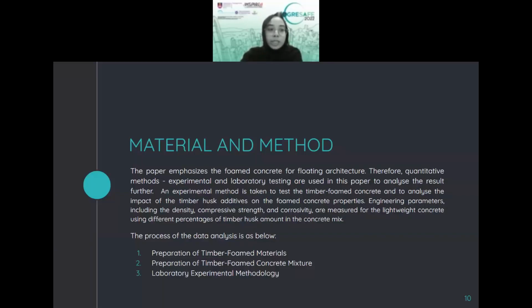And coming towards the material and methodology. In this paper, I use a quantitative method where experimental and laboratory testing are used to analyze the result further. So the experimental method is taken to test the timber foam concrete and to analyze the impact of the timber husk additive on the foam concrete properties itself.